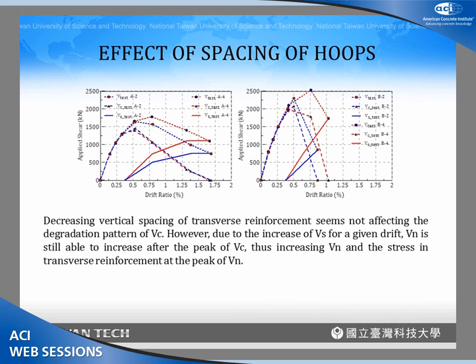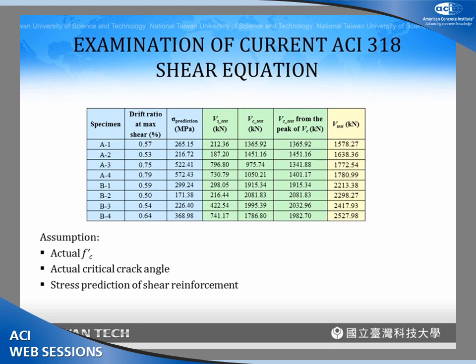This slide shows you the effect of the spacing of the hoop, and we found that if you increase the amount of the hoop, you are able to still increase the total shear strength, although the shear strength from the concrete already decreased. So this means that the increase of the amount of the transverse reinforcement will increase the stress in the transverse reinforcement. The highest level of the stress in the transverse reinforcement that can be reached in this research was about 600 MPa.